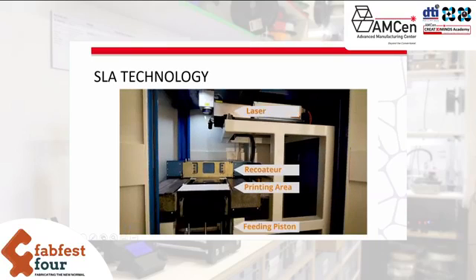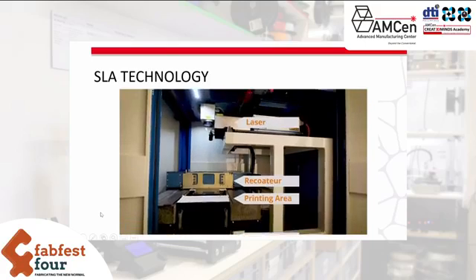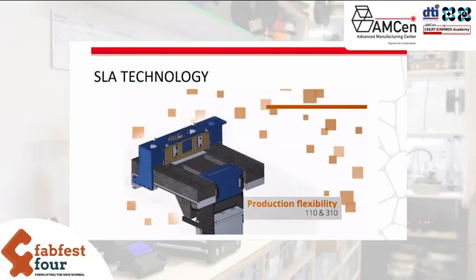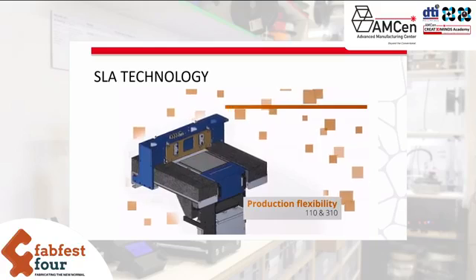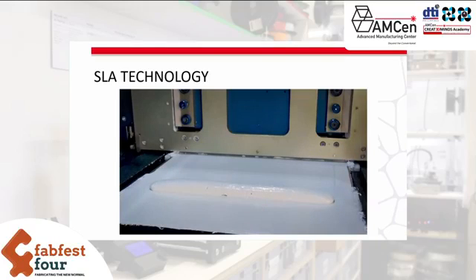Then just have a look into the printer. So you have a tank for the paste, the mix of ceramic powder and photopolymerized binder. The printing platform is in the middle of the printer. The recoater with the blade in order to spread the paste on the printing platform, and the UV laser, very low power, based on the top of the printer. I will explain later, but we can have different sizes of printing platform with this printer. You can see the high viscosity of the slurry.